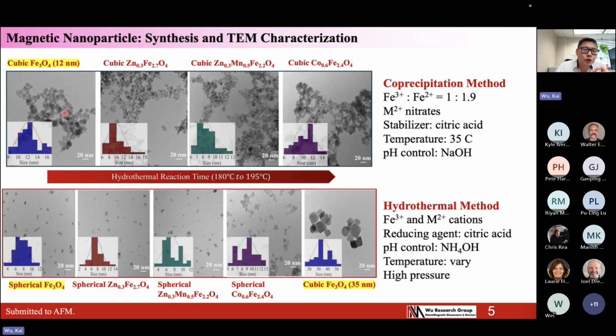As you can see, we try to produce cubic and spherical particles, but they are not as perfect in shape as we want. So we also compare with the hydrothermal method to produce nanoparticles. This method is better at controlling the size, uniformity, and shape of particles. We showcase the spherical particles produced by the hydrothermal process, and also one exception. We also produce cubic iron oxide with a very large size to compare the performance with the particles we produce here.